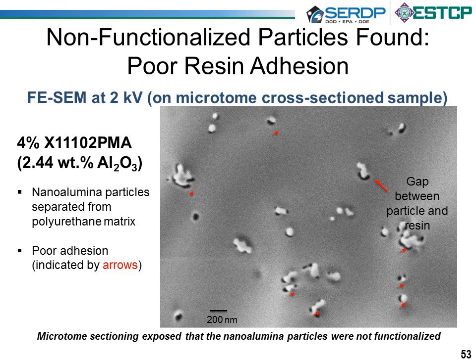When we were doing the transmission electron microscopy on the previous slide, the precursor to that is a microtome slice. It evolved out of the medical industry, where it's designed for slicing bones, but it slices these things pretty well. In the slicing process, on one side you get a very thin film used for transmission electron microscopy, but on the other side you end up with a nice smooth surface on your main mount. And we can examine that using more traditional scanning electron microscopy.